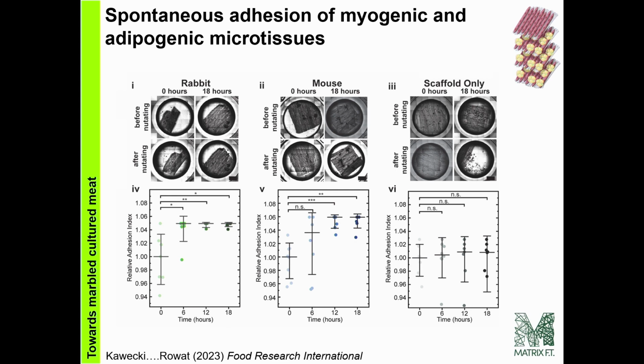So this is all showing you that this relative adhesion index increases over time, generally on the timescale of hours, for cells from different species and also different types of scaffolds. By contrast, the scaffold-only context here shows no change in relative adhesion index over time. So clearly the cells are somehow mediating the adhesion, the spontaneous adhesion of these microtissues to each other.